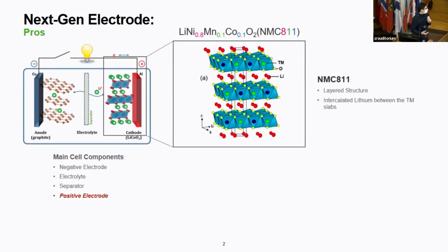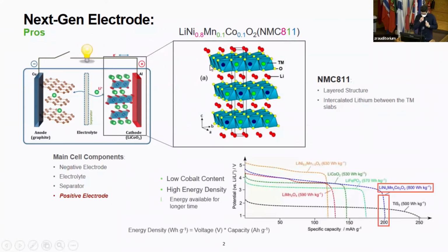My PhD project is focused on one of the components, the positive electrode, and I will work with the commercial material called NMC811, which Umicore produces. It is a transition metal oxide with a layered structure where the lithium is intercalated between these transition metal layers. Why this material is so interesting is because it has a low cobalt content. Cobalt is going to be more expensive in the future, and we want to completely remove it. And this electrode has high energy density, which means that our device or our vehicle can travel for longer distances.